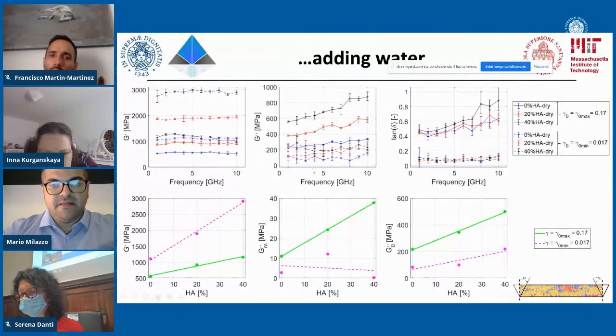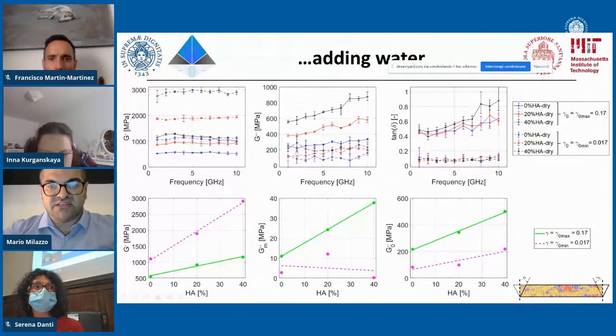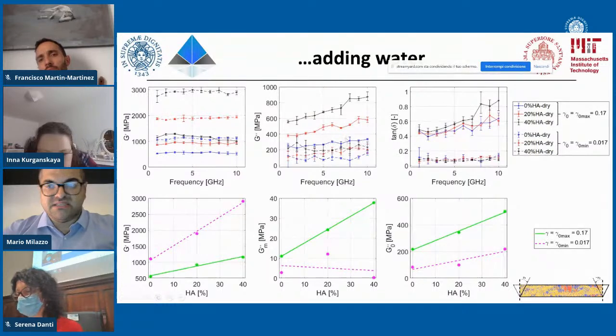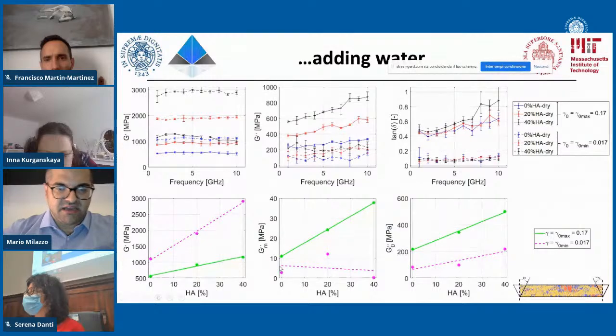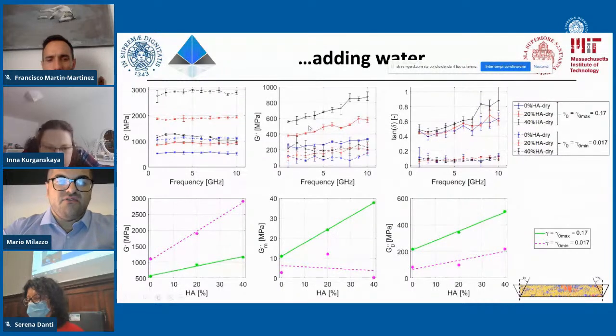The very interesting part is related to the viscous behavior of the material, because the viscous behavior doesn't show any specific trend with the lowest angular deformation. Here it is summarized by this line that is a statistical manipulation of this data, we can see that basically we don't have any trend, but we can see a specific trend for the viscous behavior against the highest angular deformation, especially after 5 gigahertz. And it's quite linear, and here is represented by this green line. The same behavior, as I was saying, is emphasized in the tan delta. It's possible to be appreciated here in this last plot.